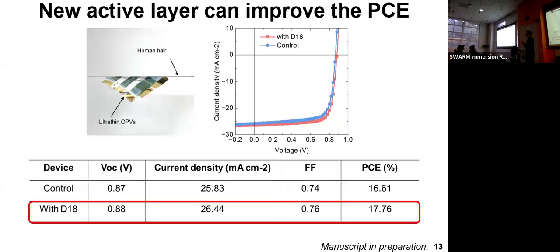Okay. Then an important aspect is materials, because organic electronic devices can be improved in performance by using newly synthesized organic materials. So recently we have been collaborating with organic chemistry researchers in a Chinese group. Then we received very good organic donor-acceptor materials from their groups. Then we fabricated very, very thin organic solar cell devices as shown here, and we could achieve high PCE values up to 17.8%.